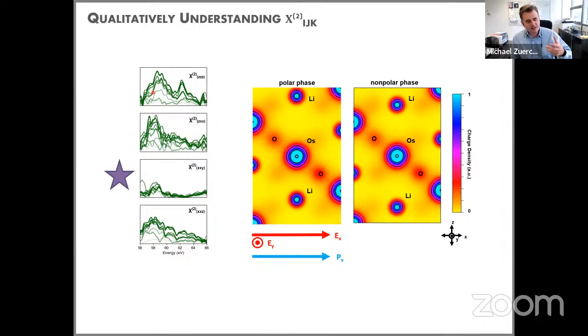You can actually select a certain direction that you probe. In our experiment, we had a combination of all 4 measured, simply by the way the crystal was oriented and rotated. And I will admit, when we did the experiments, we first did not pay so much attention to it. So we basically found this all out in the post-analysis, that we have to very carefully understand the geometry of the crystal and these projections. But in any case, this shows the possibilities that one has with this type of spectroscopy.